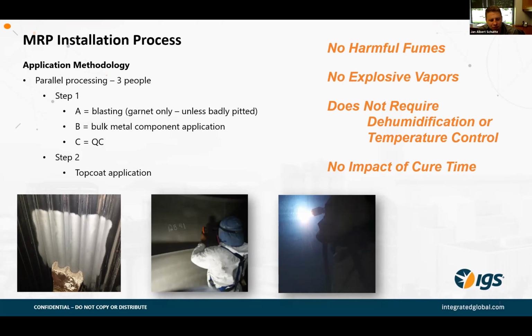So yeah, good question. So the installation process, step one, is blasting. We're looking for a white metal finish, and we typically use garnet to achieve that finish. One thing to watch out for is to assess your surface once the blasting is done, in terms of pitting or sharp edges. If any of these do exist, they need to be taken care of: sharp edges need to be removed or pitting needs to be opened before HVTS gets applied. So that's the first step. Blasting is white metal finish.